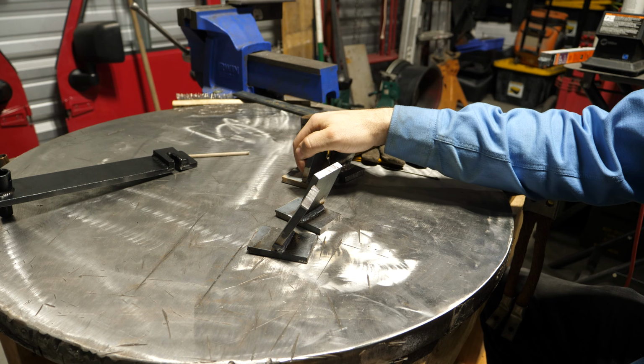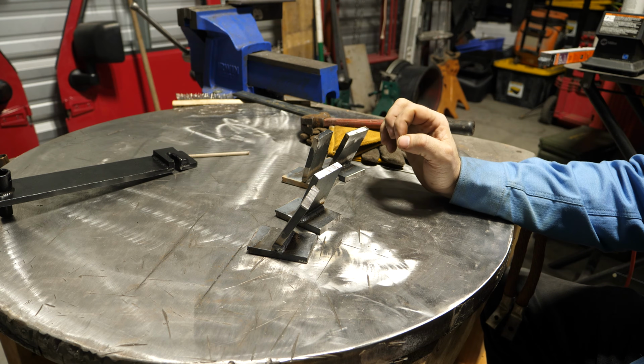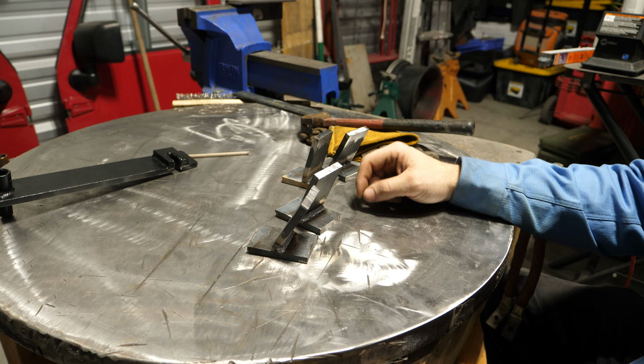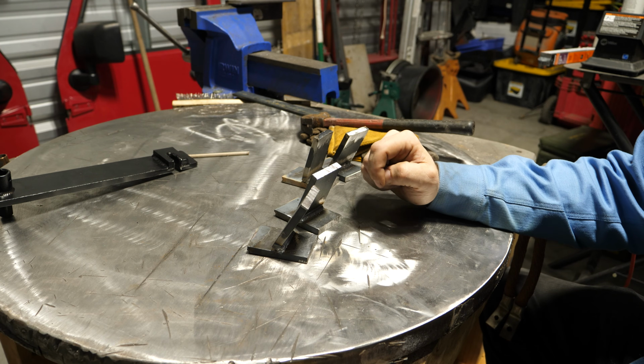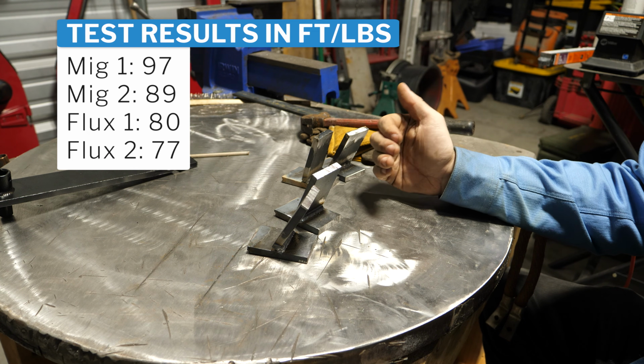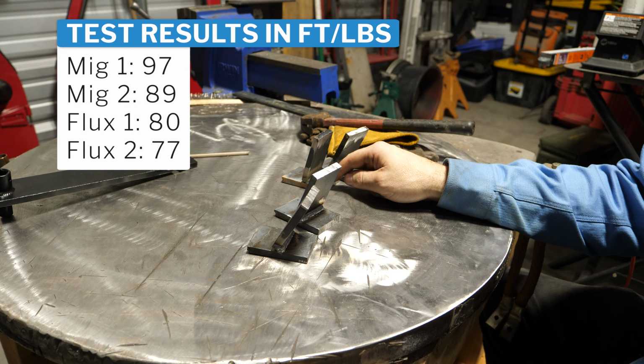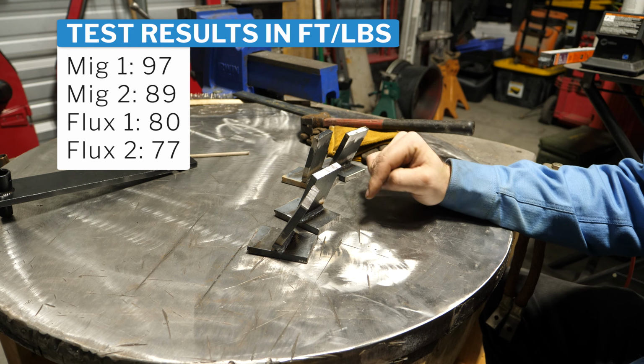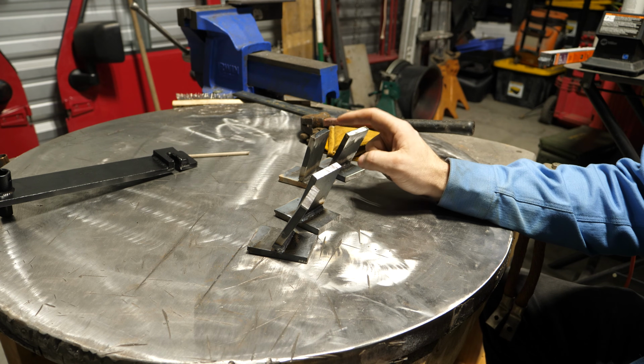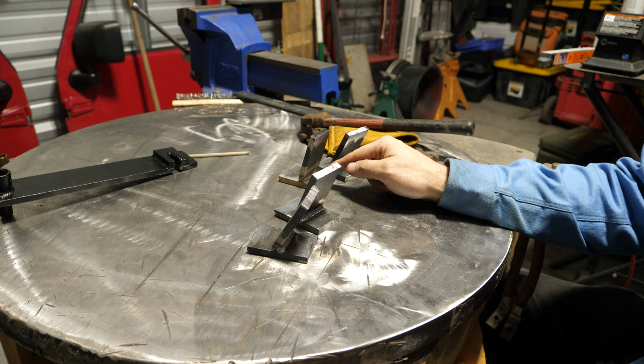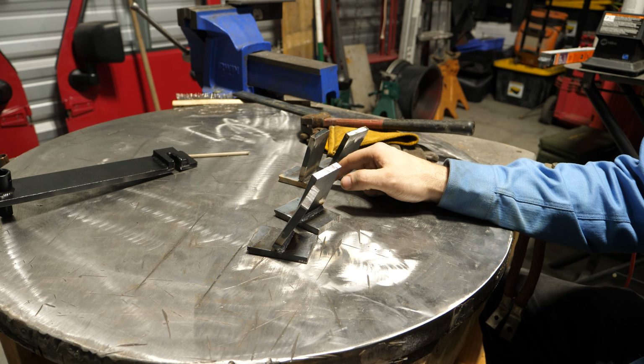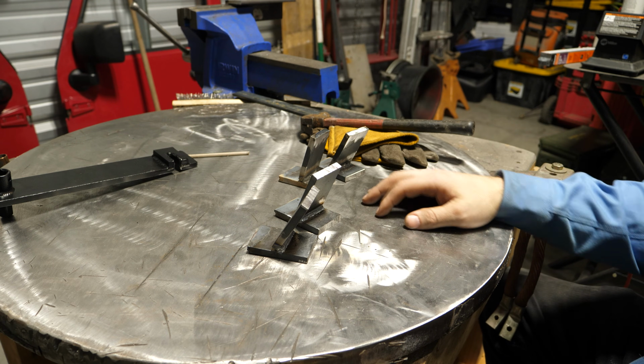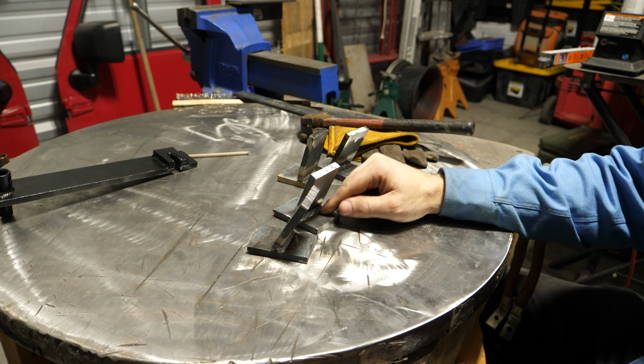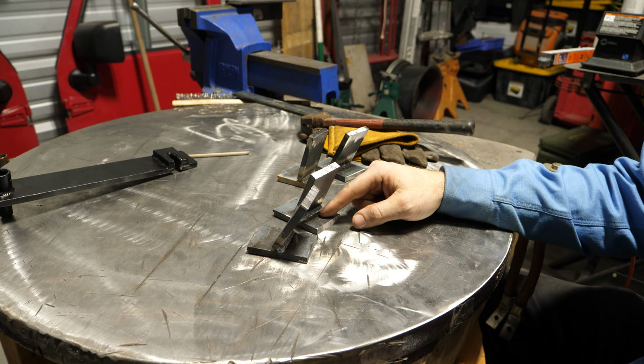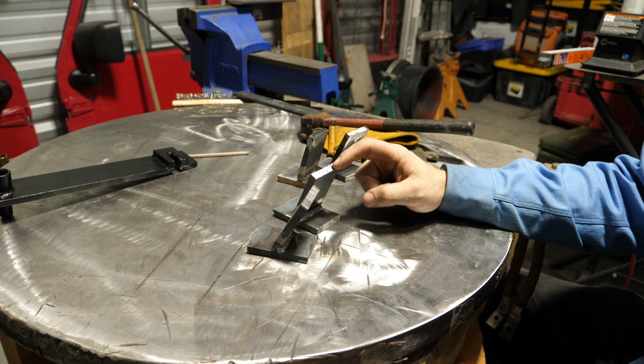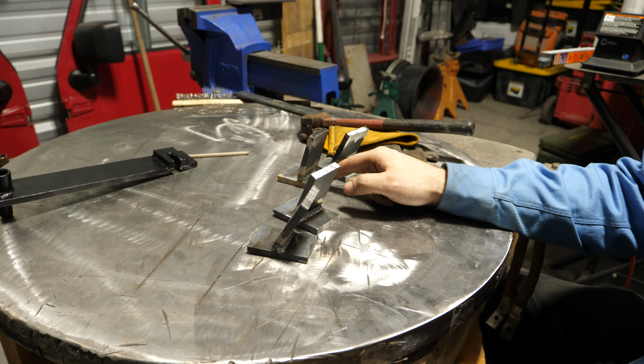We saw that the flux core welds actually broke at less torque, or less foot-pounds, so less force than the short arc MIG. I think, at least in theory, we're going to see more penetration on the flux core welds, but I believe that the result of this being weaker had more to do with the weld size than it did the process itself, I guess, is the best way I could describe it. Because these welds were smaller than this, the leverage effect played a bigger role to help this than likely the higher penetration for this.